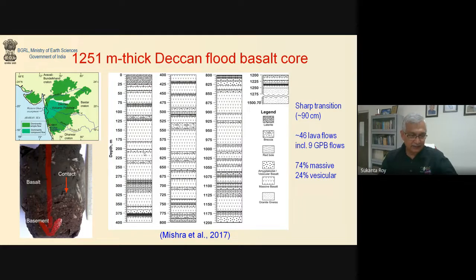On the left hand side, you can see that the contact is so sharp between the basalt and the basement rock. As I told you, the basalt essentially sits directly on top of the Precambrian basement here. We were able to do a logging of the core, and we were able to identify from physical studies, from megascopic studies, about 46 lava flows, including 9 giant plagioclase basalt flows. 74% of this trap layer was massive, and 24% vesicular, and so on.